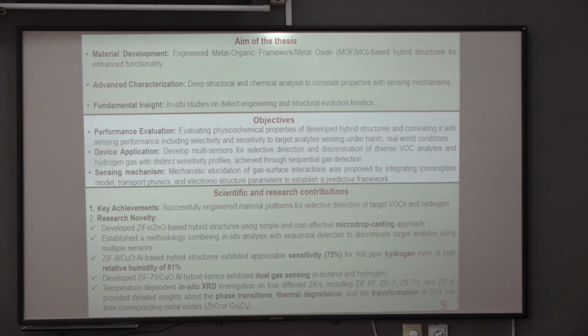The key novelty of this work includes micro drop casting, which is low cost, cost effective and easy to use, and for the hybrid system ZIF8 copper oxide aluminium, which provides appreciable sensing response towards hydrogen even at a high relative humidity of 81%. Using ZIF71 copper oxide aluminium, it exhibits dual gas sensing for N-butanol and hydrogen at different operating temperatures, and using advanced characterization tools, we get insights about phase transitions, thermal degradation and their respective transformation in metal oxides.